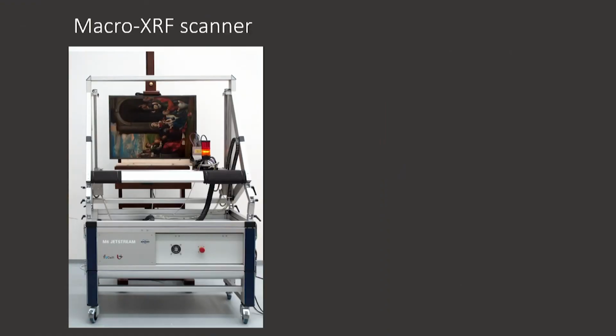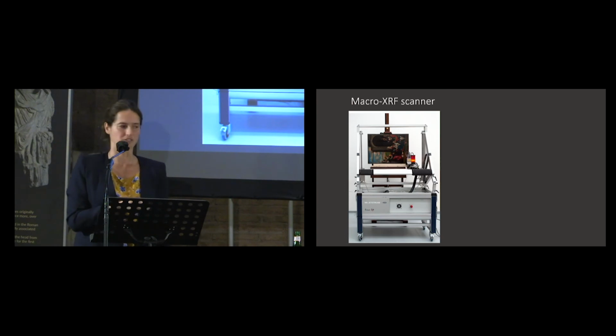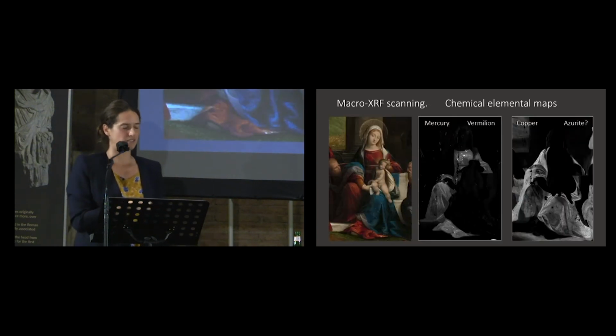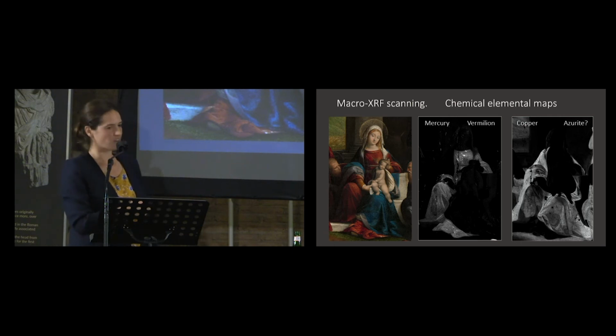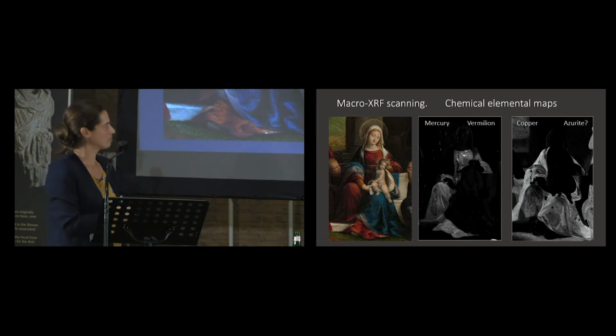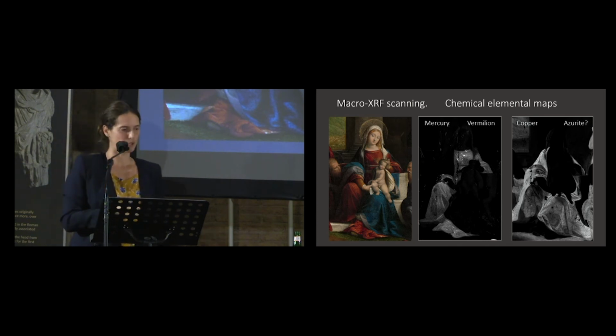This sparked our enthusiasm, and we decided to take the research further, looking at in-house available techniques such as macro X-ray fluorescence. This technique delivers chemical elemental distribution maps, but still we could not make sense of all the pentimenti that occurred. The copper map, for example, can relate to various copper-containing blue or green pigments, as we all know, and so we saw that there is some blue pigment here, but we could not make sense of the entire